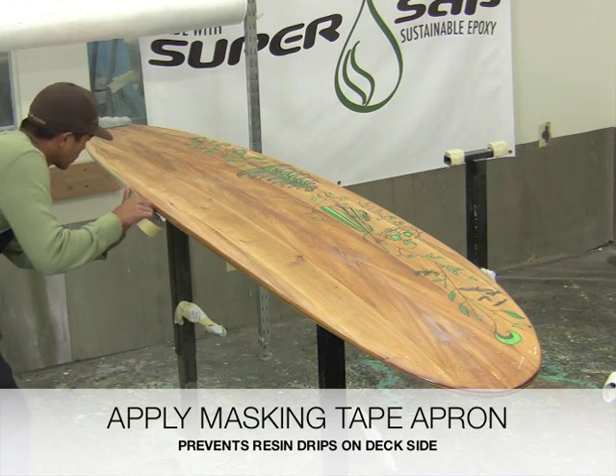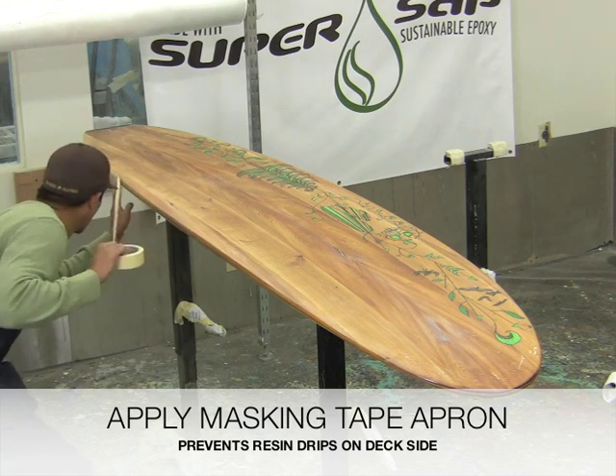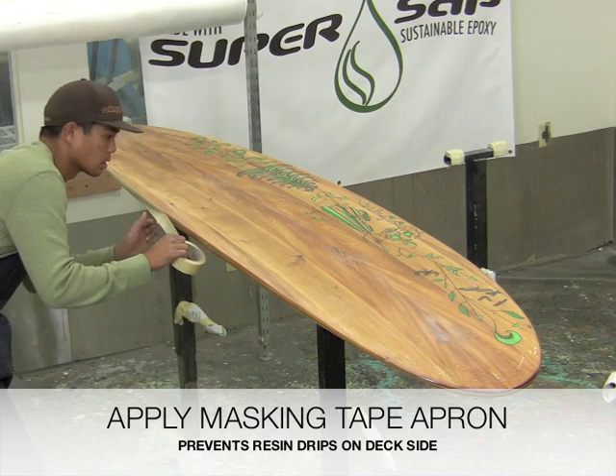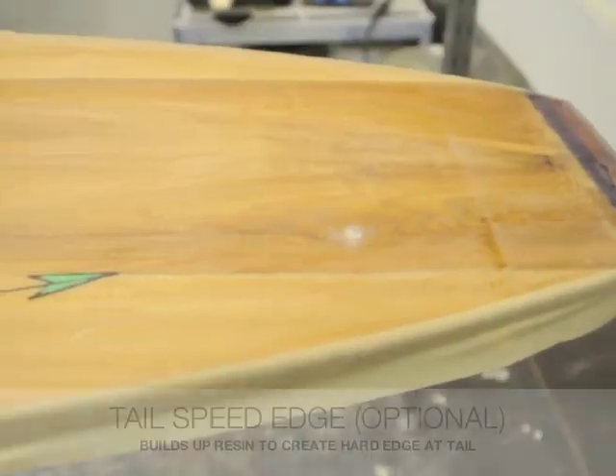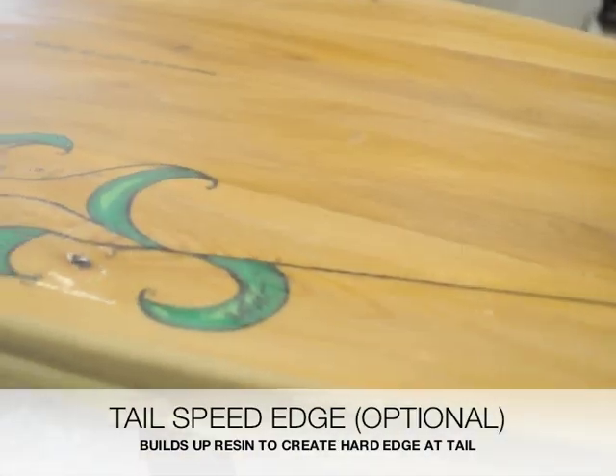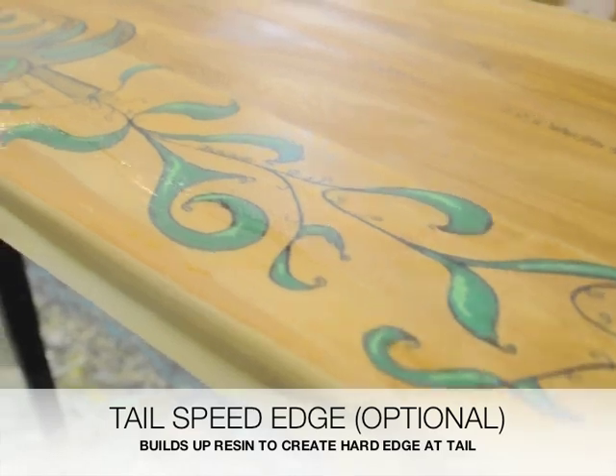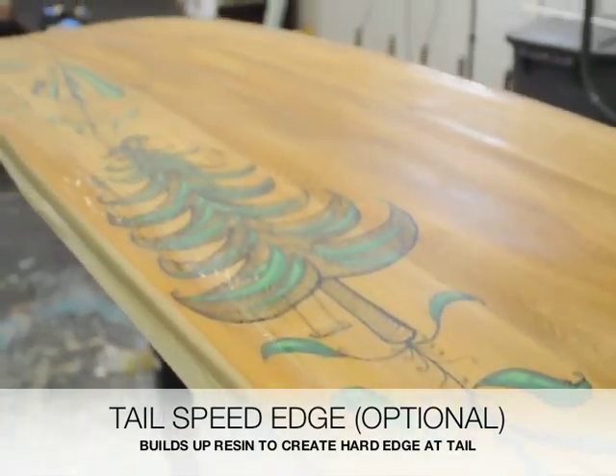Apply a masking tape apron around the perimeter of the board at the apex of the rail to avoid getting resin drips onto the deck side. A speed edge can be built up by applying the tape higher than the board surface at the tail.